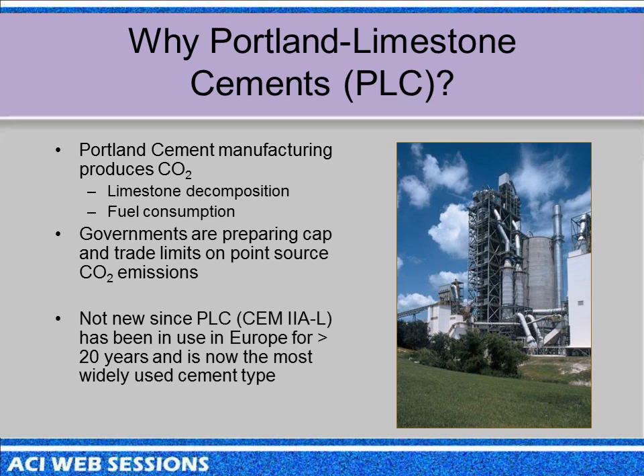This is not a new concept. It's been used in Europe since the 1960s. I think Heidelberg in '65 was the first one to make limestone cements. It's been in the European standards since they've had the combined EN standards. And they have two types of limestone cements: CEM II/A-L, which has up to 20% limestone in it, and CEM II/B-L, which has up to 35% limestone in it. And it's now the most widely used type of cement. Limestone-containing cements in Europe are now the most widely used of all the cements being produced in the European countries.